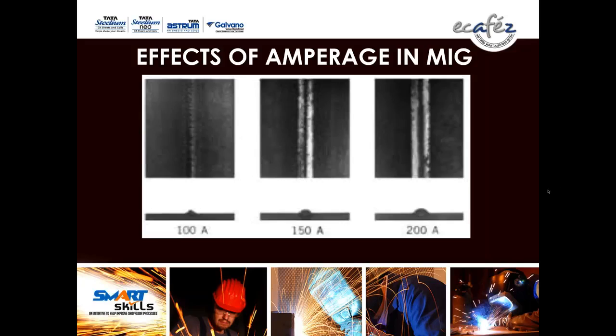How to reduce the bulging in SS 1 millimeter sheet during the MIG welding process? For 1 millimeter thickness you have to use a pulse machine. But it is better to use the TIG welding process with back purging on the underside of the weld. You'll get very good quality welding.